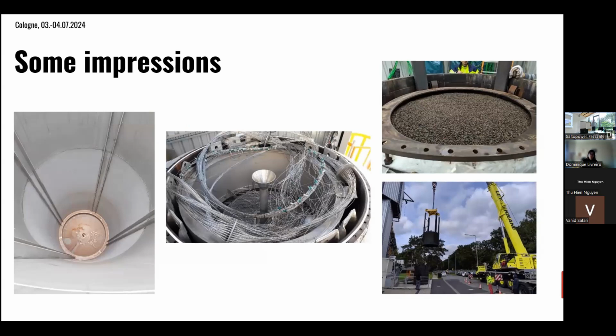Here are some pictures. On the left you can see a look inside of the storage tank. Then on the right you can see where we were putting the filler material inside these baskets into the tank. They have some large handles, and then we have an auto crane coming up and lifting everything into the tank. Here you can see the top of the tank after the 3rd basket was stacked in there. Finally, on top there's a distributor device for the salt to evenly spread the salt when it's coming from the top. You can also see somewhere here on the right the outflow, and obviously we are putting in a lot of thermocouples because our main interest is to measure the temperatures inside of the tank.